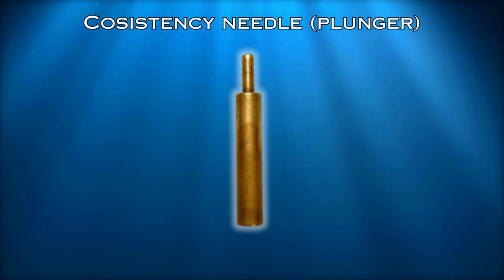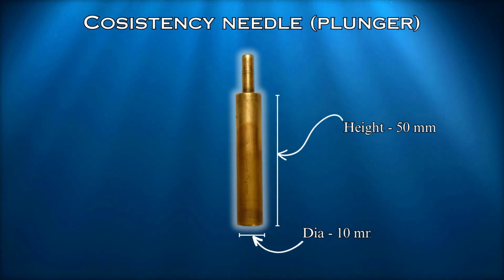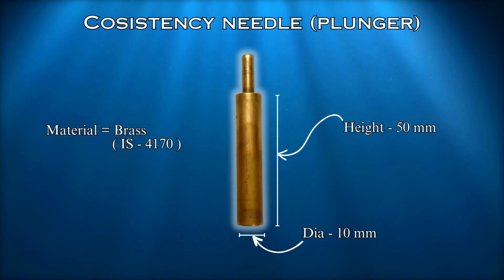Second, the consistency plunger should have a length of 50 mm and a diameter of 10 mm. It must be made from brass in accordance with the Indian Standard IS 4170.